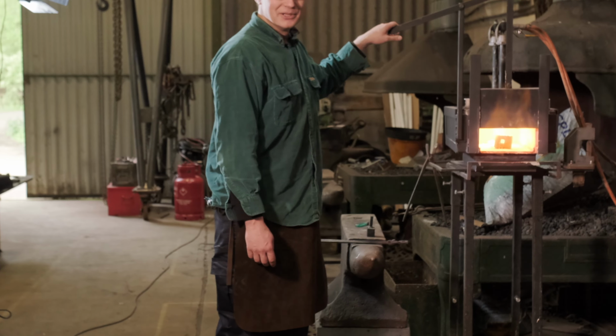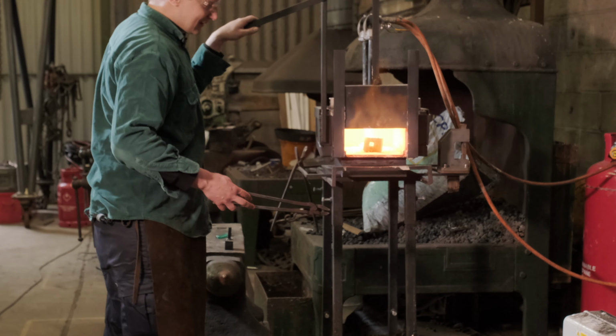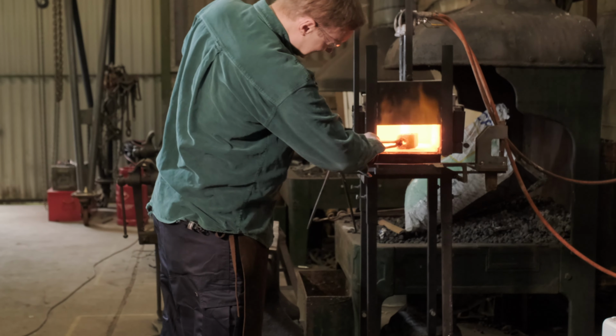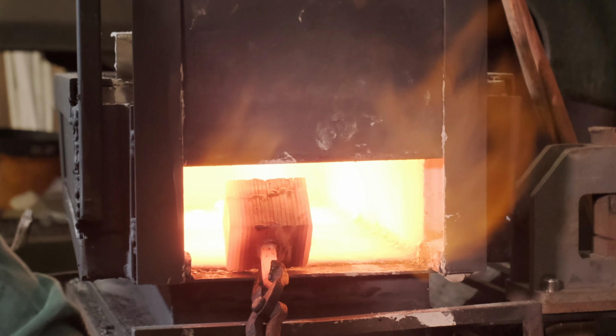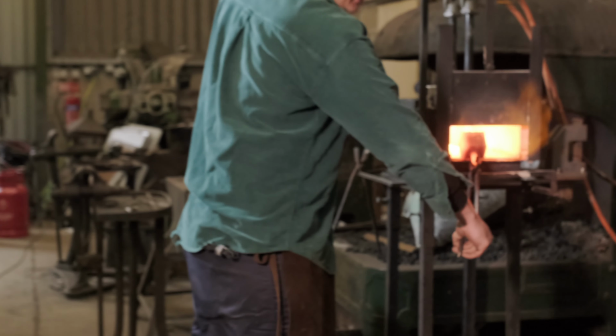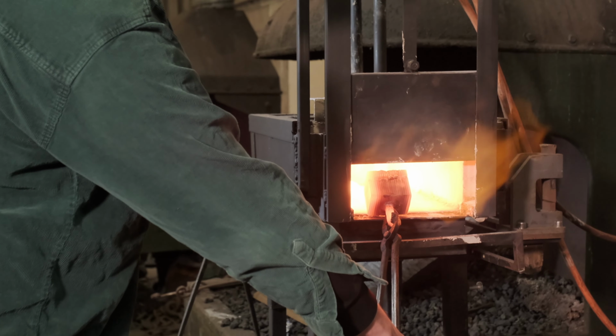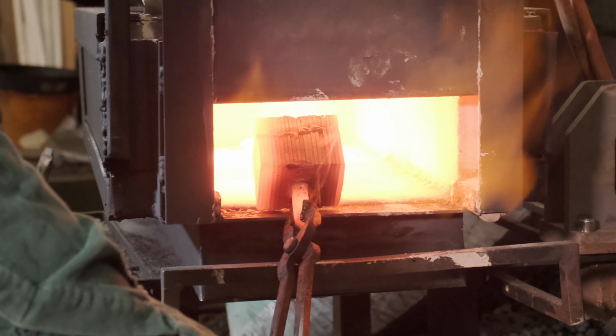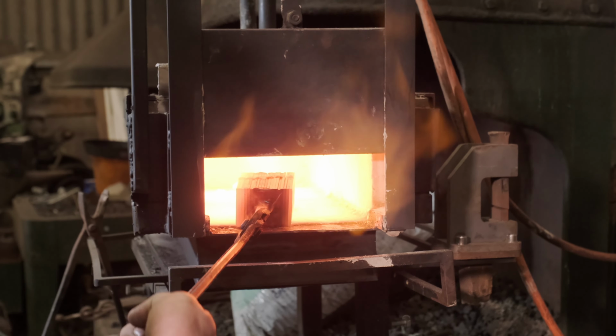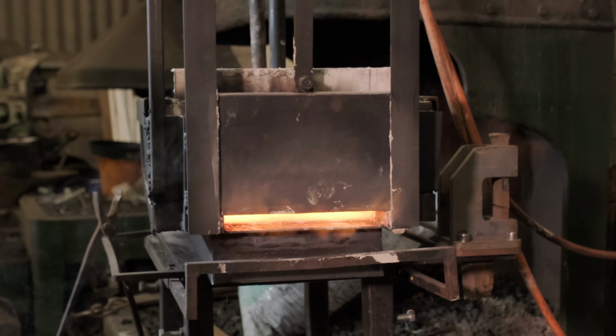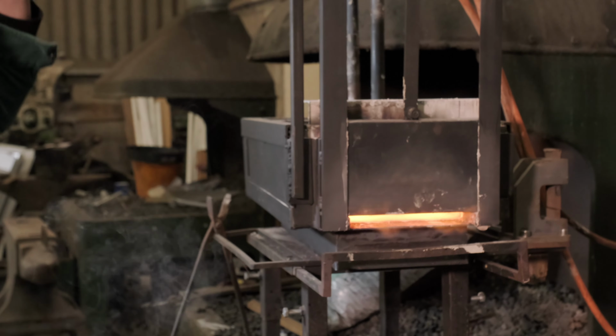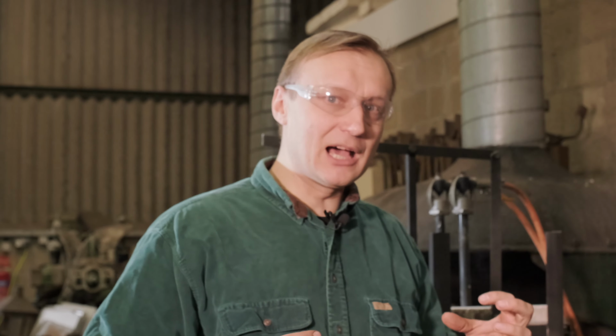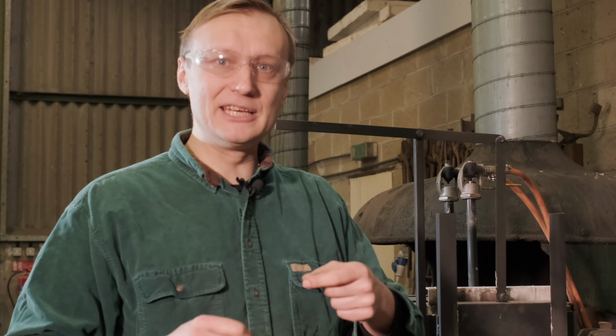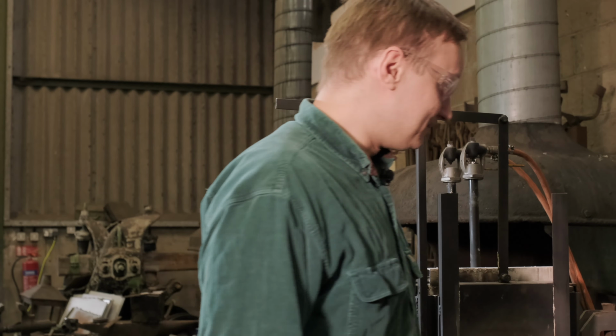So it starts to heat up. You can clearly see how the heat transfers into the stack. On the outside much hotter than on the inside. So we're pretty much ready for a first step. What I would usually do before it gets completely heated up, I'll get it on the power hammer and just gently hit those layers nice and tight together, so if there's any gaps, they're basically closed off.